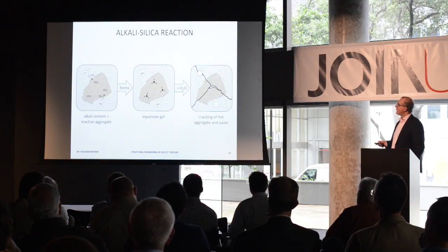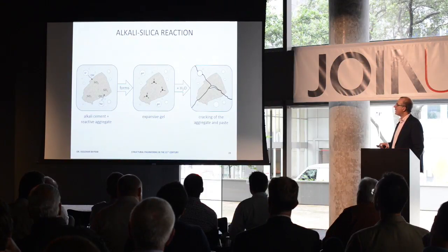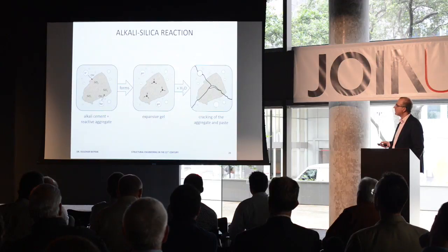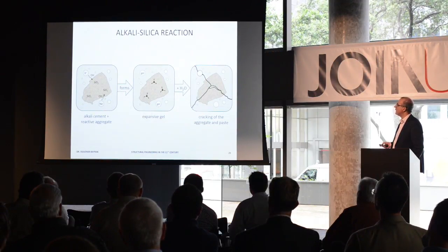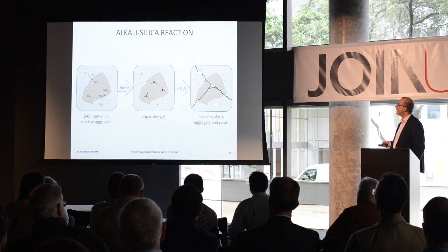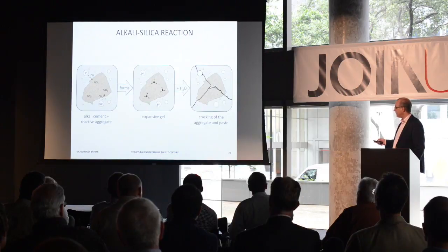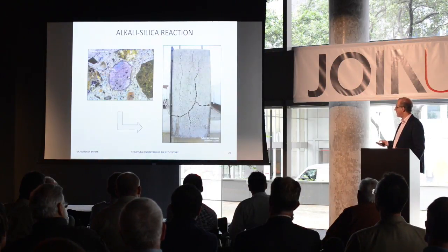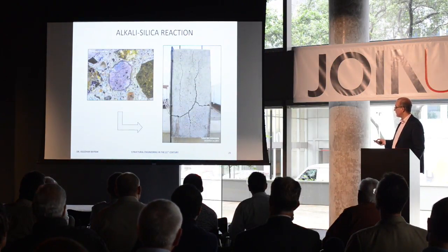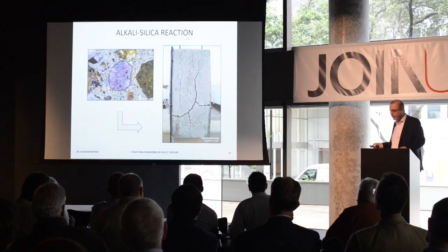In a nutshell, ASR is nothing more than having a high alkali pore solution and a reactive aggregate, and a chemical reaction that takes place at that level produces an expansive gel, and when that gel absorbs water, it does cause cracking, and when that cracking is in place, basically you may have a structure or a structural component that may look like what's shown on the right-hand side.